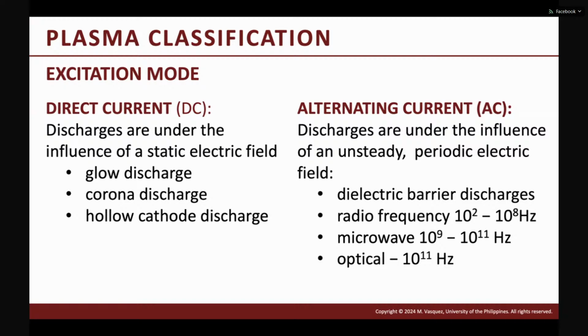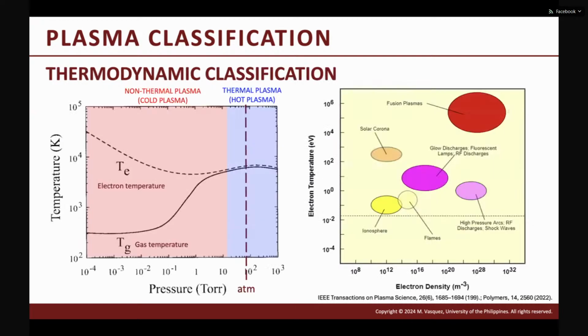Now, between DC and AC, in DC you have limitations in terms of the use of electrodes because they should be conductive. Unlike alternating current, you can use different materials from conductive to non-conductive materials. For direct current, the plasma is low density but high energy. Unlike in alternating current excited plasma, the density is high, but the energy is relatively low.